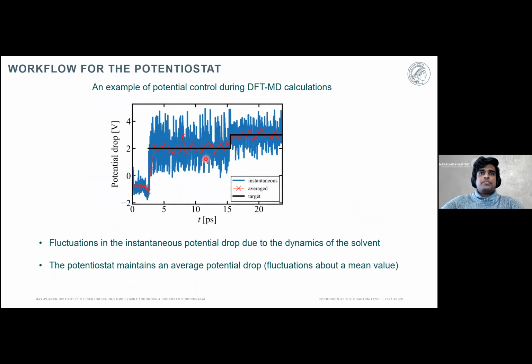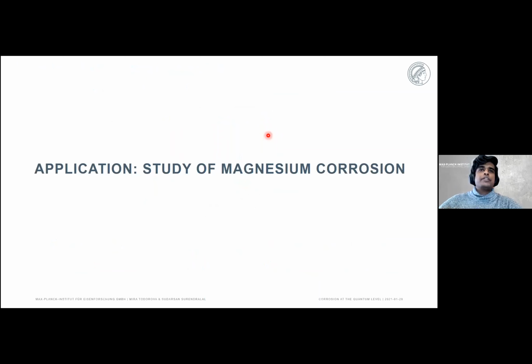As a consequence of this mixing algorithm, we are able to maintain a given average potential for a trajectory. This is an example of how the fluctuations in the potential would look in a typical potential-controlled molecular dynamics simulation. You can see the blue instantaneous value of the work function fluctuates due to the dynamics of the system. However, the average potential drop is maintained by the potentiostat. This is what a computational potentiostat does. So we now have a potentiostat which actually helps us do these simulations.